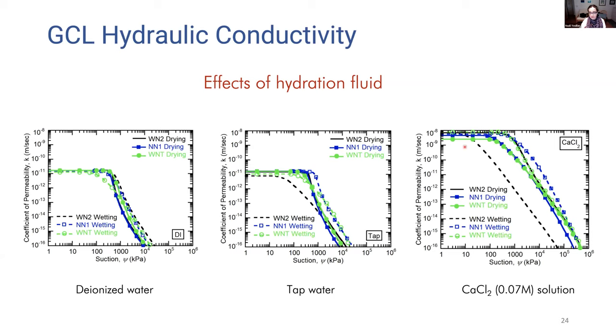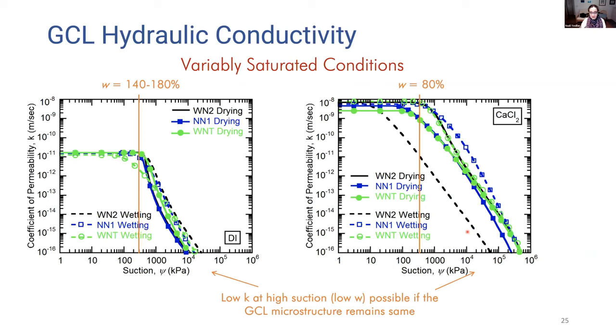And again, there's a significant difference between the two types of curves as a function of the solution that's used in the analysis. In the next plot, I have highlighted results from the DI water, deionized water, and calcium chloride solution tests. I put the approximate moisture contents when the change in hydraulic conductivity occurred. For this case, this is somewhere in the 140 to 180% range. And over here, we have the moisture content at about 80%, after which the hydraulic conductivity or coefficient of permeability